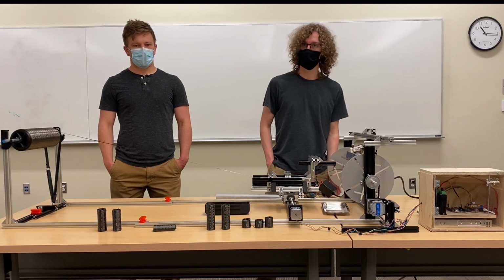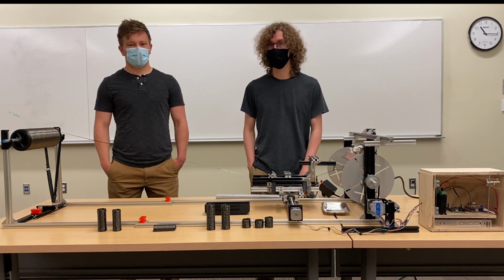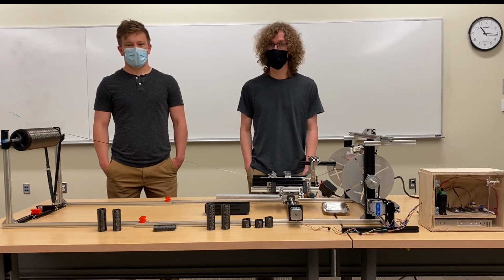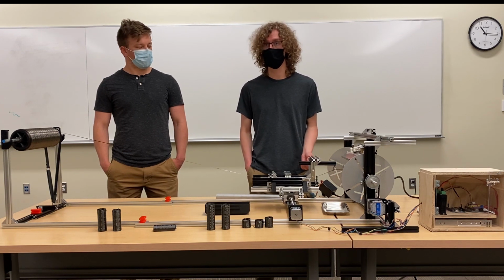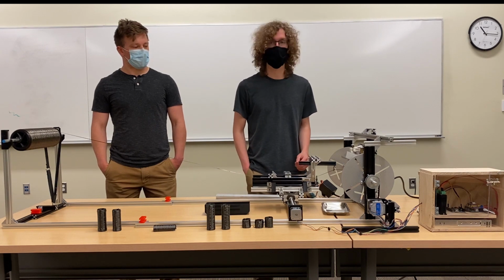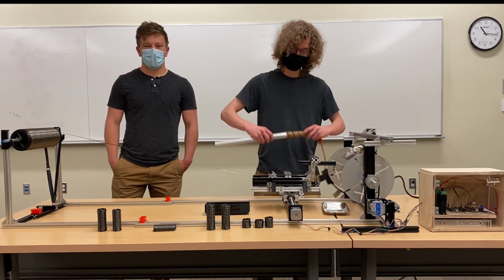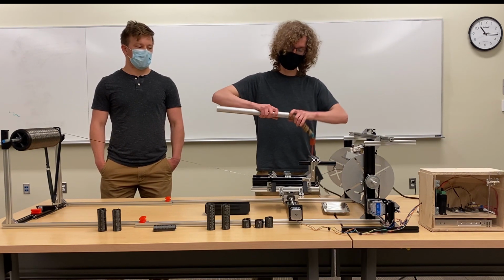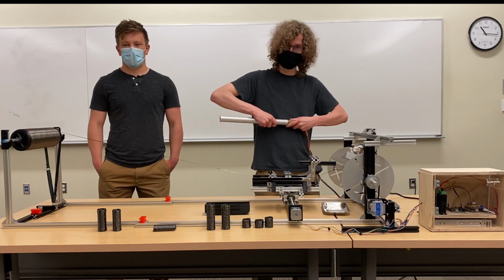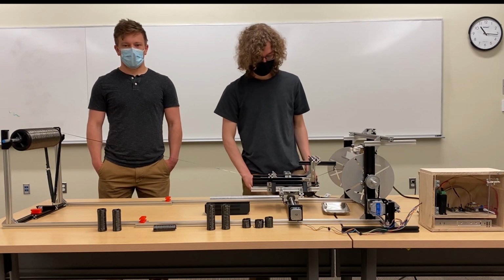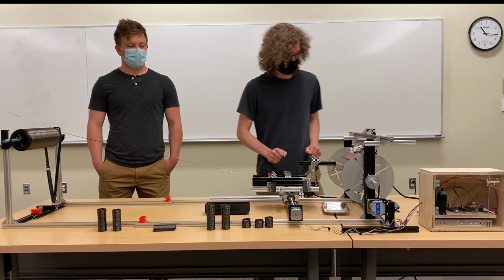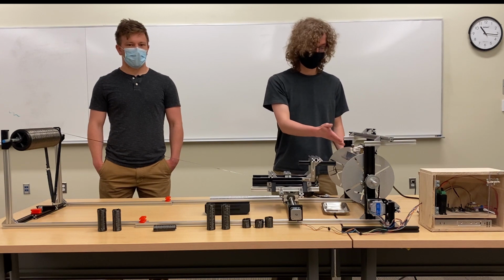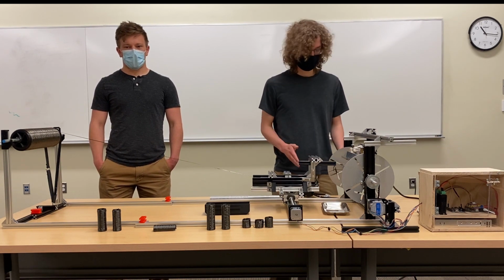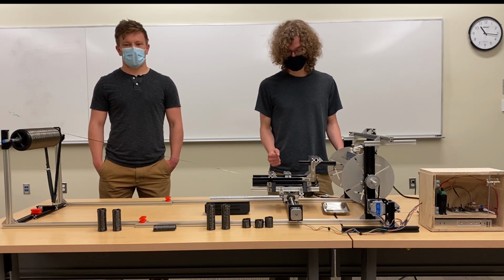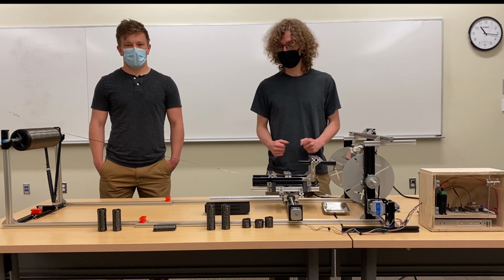To remove the secondary curing stage, a novel formulation of DCPD resin was used as the binding polymer. This resin quickly undergoes an exothermic reaction that cures the composite fully once the part begins to reach a temperature of approximately 70 degrees C. In order to cure the wound part, we explored two different heating methods. The first is a resistive heater that's simply inserted directly inside the mandrel to heat the whole surface. This produced parts very quickly, however it had some issues. The second is an infrared heater, which is placed above the mandrel, providing radiative heat transfer. This cured slightly more slowly than the resistive heater, however the mandrel could continue rotating, mitigating some of the issues that Aiden will speak about.